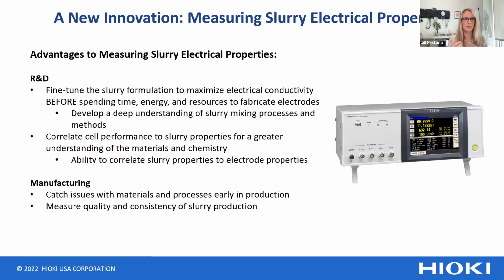And so by adding this ability to measure the electrical properties of the slurry, you can do a lot of work to fine tune that slurry formulation to maximize its electrical conductivity before you spend the time and energy and resources to make the electrodes. And so not just like developing a better electrode, but you have more parameters, more measurements that you can use to understand slurry mixing processes and methods and improve those processes. And you can also start to perhaps correlate that cell performance itself to the slurry properties for a greater understanding of materials and chemistry. That can really accelerate R&D as you get those answers.